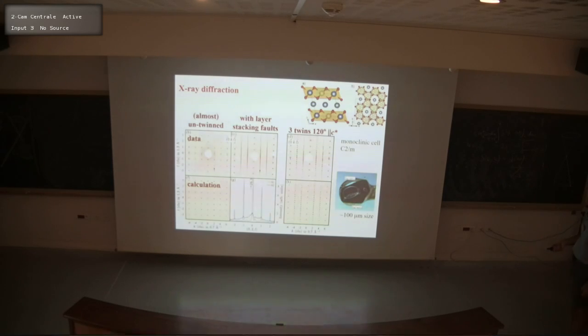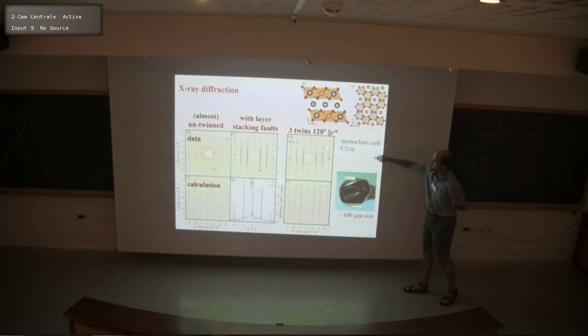However, if the growth conditions are improved, then this has a massive change into these very sharp peaks that we see here. So this is a high-quality sample which is untwinned. Also, these materials suffer from the fact that they're almost close to threefold symmetry, so then many twins form, and here is a sample which had 3 twins rotated 120 degrees, which gave rise to all of these extra peaks here.